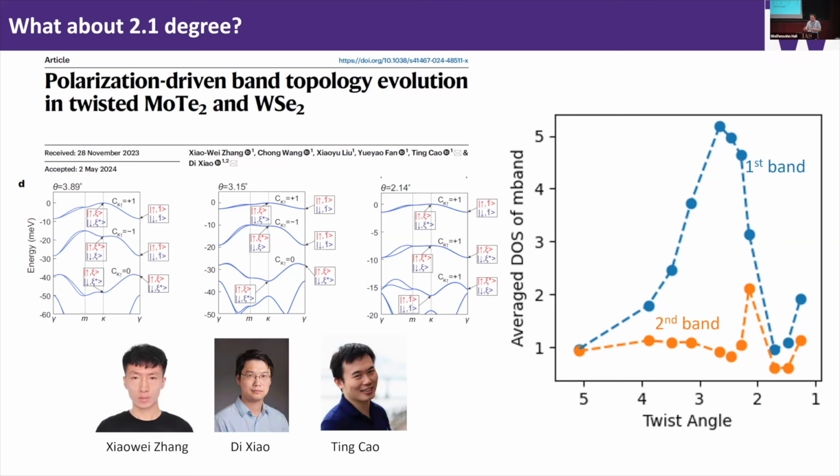So they all worked on these 2.1 degrees, but it turns out that it's very challenging to make a good transport sample because at small twist angle the lattice relaxation becomes significant, and it's very difficult to make a good sample with homogeneous moiré disorder, number one. And the second is that most of the time the sample just relaxed. So we don't get good samples.